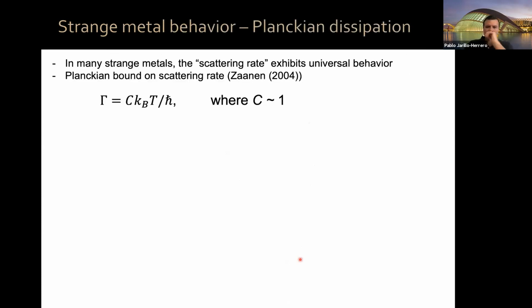Now, in many strange metals, the scattering rate exhibits a sort of universal behavior. And Zaanen speculated that there might be a Planckian bound on the scattering rate. That means the scattering rate reaches a value which is k_B T over h-bar times a coefficient, and this coefficient is of order 1.